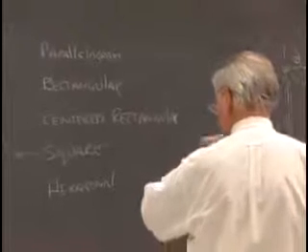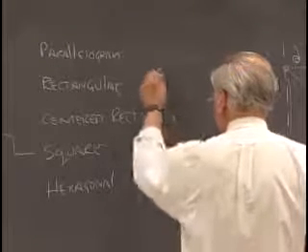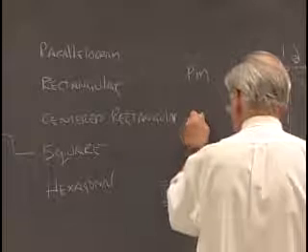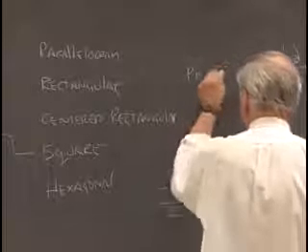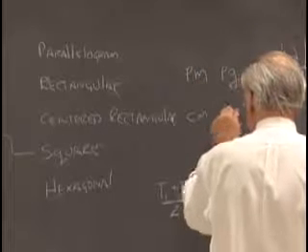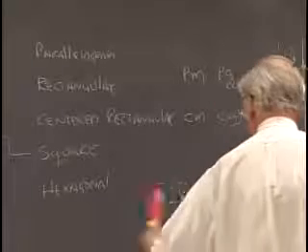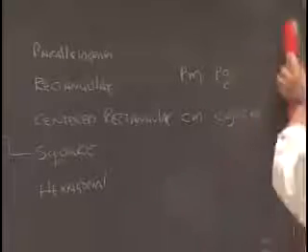Okay, so coming out of this consideration, we have with the rectangular nets PM, CM, PG, but CG, if we tried to construct it, was the same as CM. And that exhausts the possibilities for a single symmetry plane and the rectangular nets.